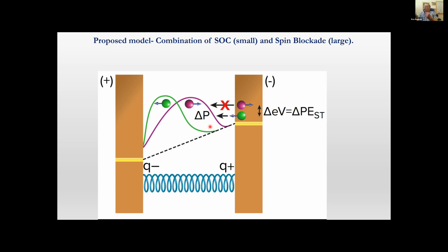So we realize here that due to the polarization of the molecule, we get, if you like to call it, a spin blockade that hinders the injection of the wrong spin into the system. And this type of spin blockade enhances the polarization as I described in the beginning, which is basically a linear effect. So we have here a non-linear effect due to the polarization and then for the spin injection.